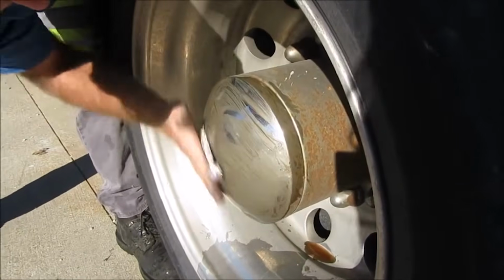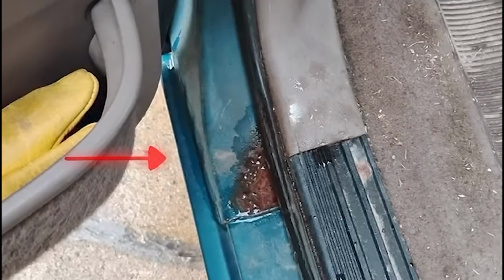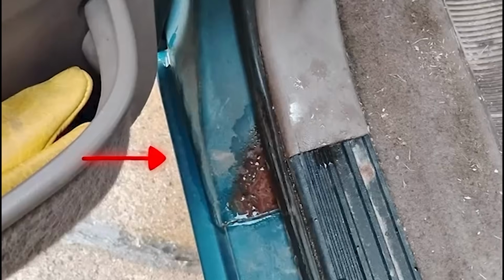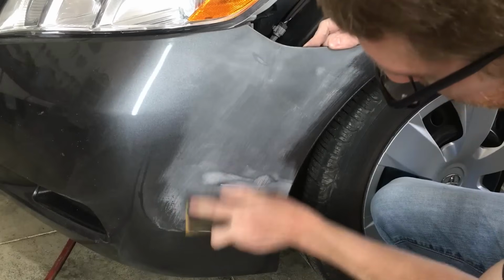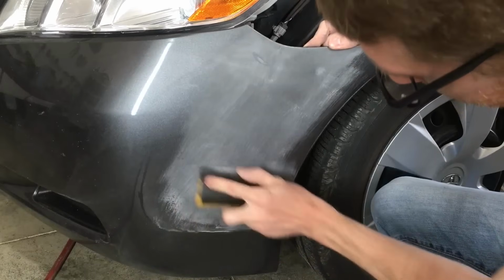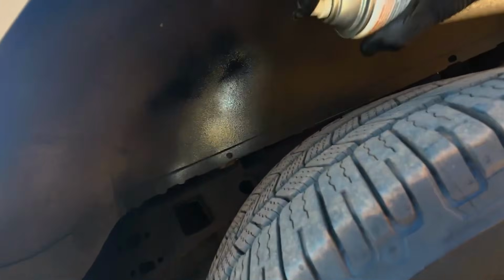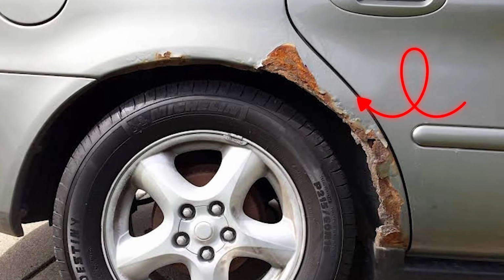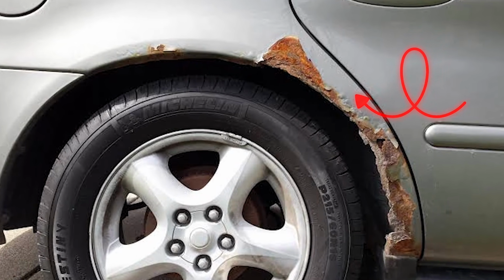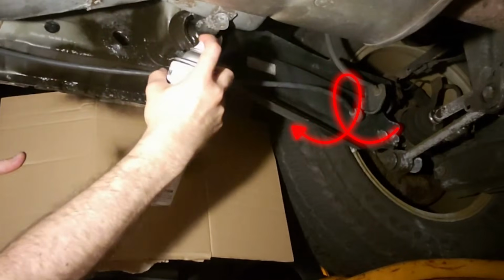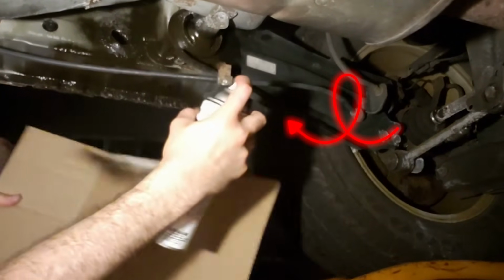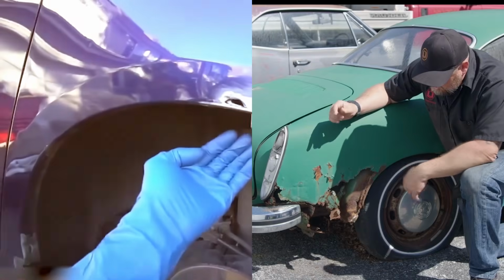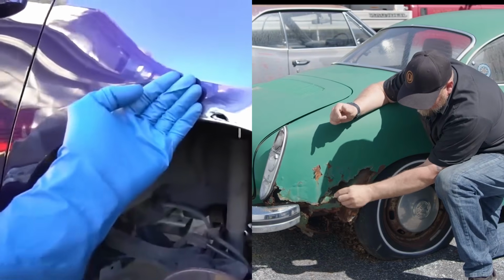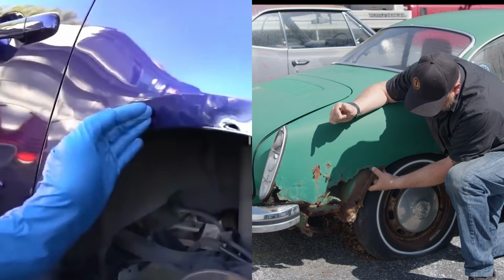beneath the converted surface. At 3 months, the converted surface layer began lifting at pit locations as the subsurface rust expansion broke the iron phosphate layer from beneath. The appearance of a treated surface masked ongoing structural damage, and the truth is that most frame rust on northern vehicles has progressed well beyond light surface rust by the time the owner notices it. The next product attempts to solve the penetration limitation with a much stronger acid formula. The results are better, but they come with a risk that almost nobody mentions in the product reviews.